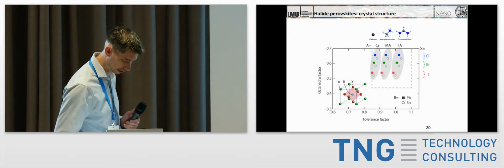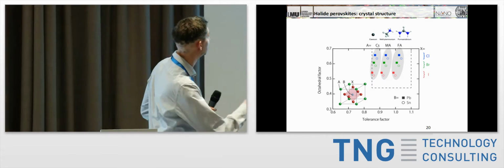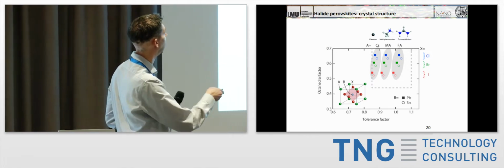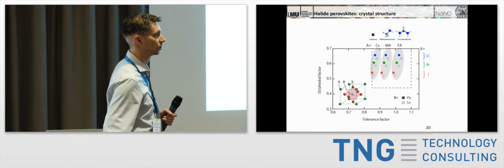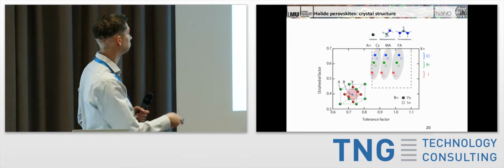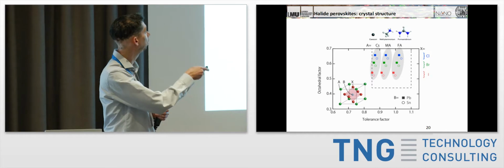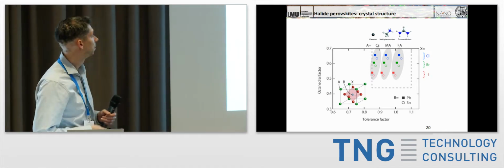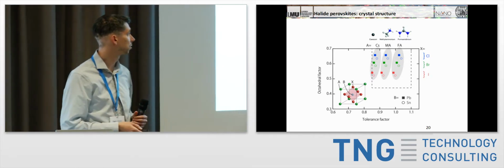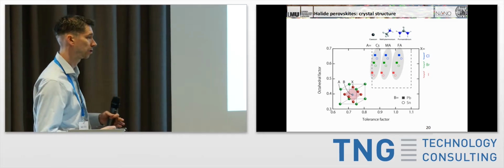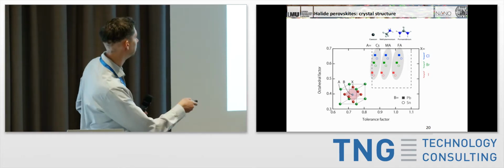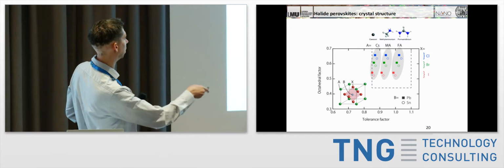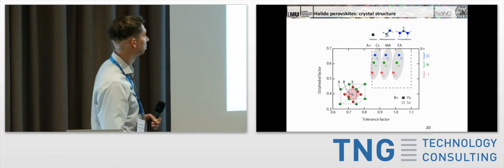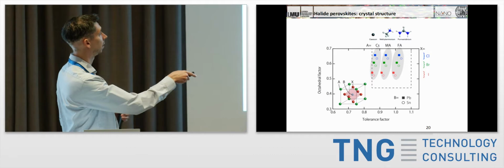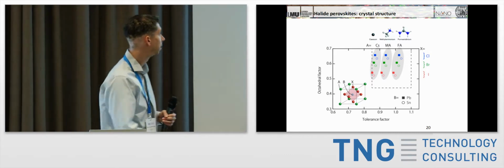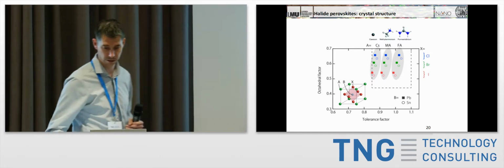Okay, so the materials that have gotten the world really interested now don't only contain single ions, but contain organic molecules that are sitting here. These sit in the octahedral voids in these A spaces, so there's methylammonium and formamidinium. These are basically the only real molecules that can fit in these spaces. Anything slightly larger than that wouldn't fit in there. You can see again here, fitting on the tolerance factor versus octahedral factor, these different combinations fit nicely in there with the different halides, the chloride, the bromide, and the iodide, and the different A ions sitting in there.